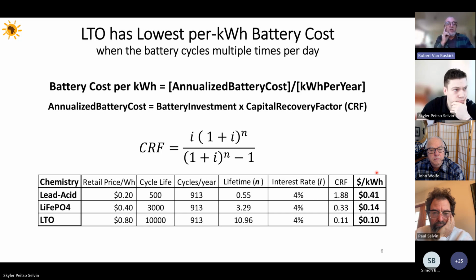with different costs for different battery chemistries, so here we estimate from surveying the market in Malawi that the lead acid batteries are running at about 20 cents per watt hour. We'll see later in the talk that our LTO battery is about 80 cents per watt hour, and we're roughly guessing that the lithium iron phosphate battery would be about 40 cents per watt hour. We don't really know, because the lithium iron phosphate isn't being distributed in Malawi very much, so it's hard to find lithium iron phosphate batteries being sold.